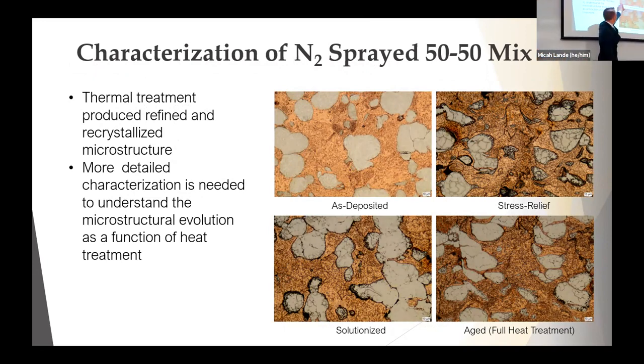In the top here, we can see things are pretty light. We don't see a whole lot of extra stuff. Just for reference, the copper color is obviously our copper alloy, and the grayish color is our HR1 alloy. As we go through here, we can see the start of a lot of distinct boundary layers in between, and we also see our copper beginning to darken more and more, because those chromium niobium precipitates are growing through the heat treatment process, and so they're looking a lot more apparent. And that's true all the way throughout. So there is definitely a change.